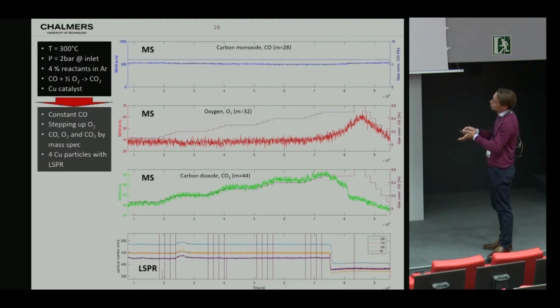And what you see is the following things. Well, as we start to supply oxygen, indeed, we can measure the product formation. But you can also see that we don't measure any oxygen until a certain critical point, which means up to here, we are completely consuming the reactant, oxygen, which is in deficit here, to the formation of carbon dioxide. And then you notice that at a certain oxygen concentration, we start to see oxygen coming out, and at the same time, we start to see a distinct decrease in the activity of the catalyst.